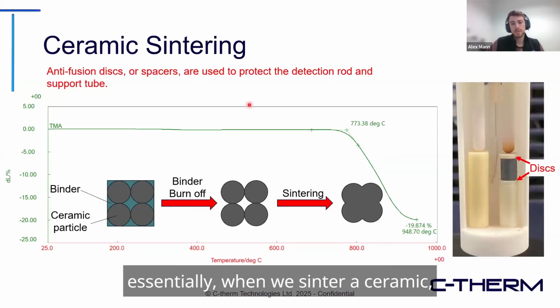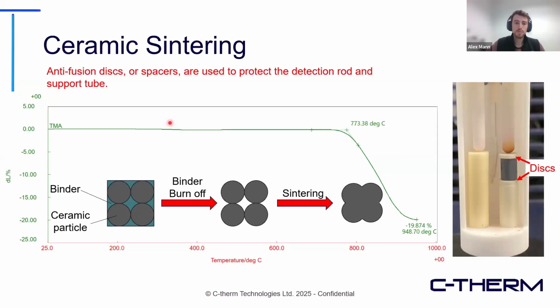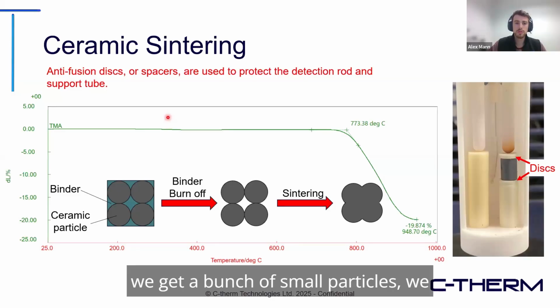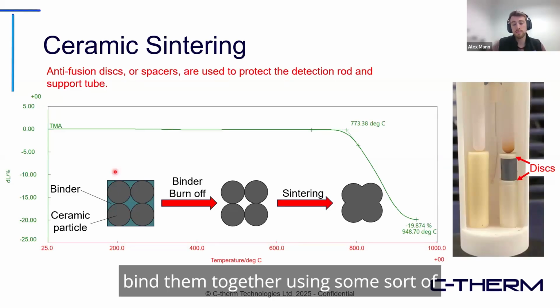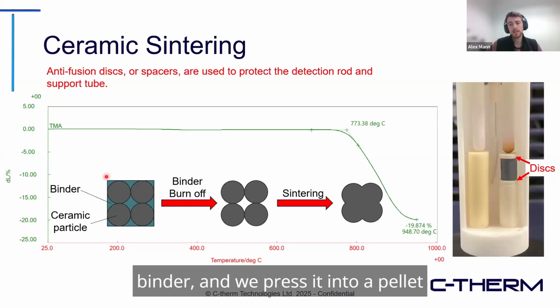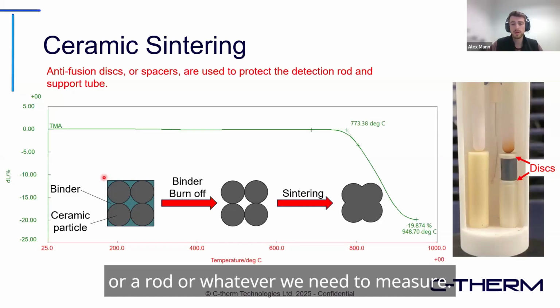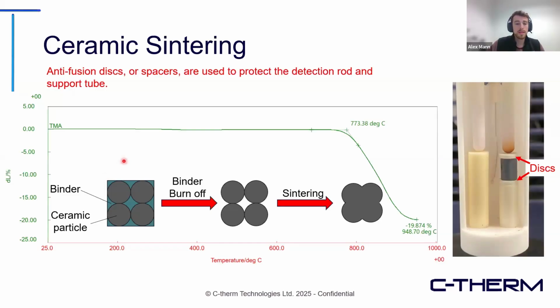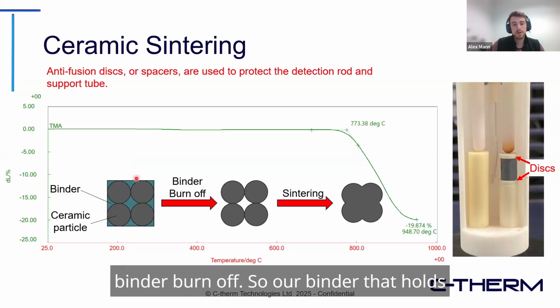Essentially, when we sinter a ceramic, we get a bunch of small particles. We bind them together using some sort of binder, and we press it into a pellet or a rod or whatever we need to measure. And then as we heat it up, we first get binder burn off.